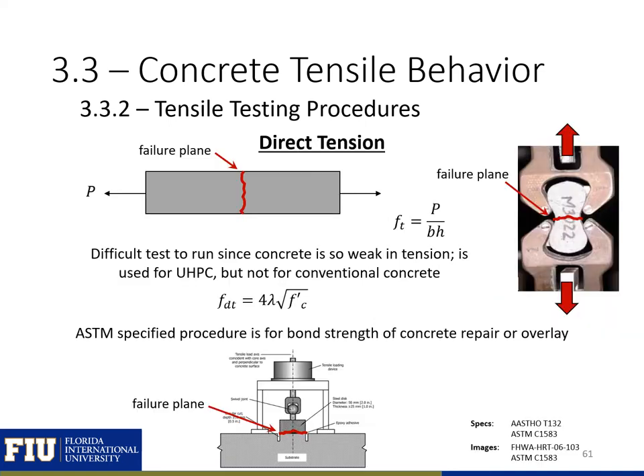The last way that tensile strength can be measured is using a direct tensile test. This test involves applying a tensile load to the concrete until the specimen fails in tension. The tensile strength can then be found by taking the failure load divided by the area of the failure plane. This is a difficult test to run for conventional concrete because it is such a low tensile strength. The low tensile strengths do not allow for any load redistribution. So if the load is applied even the slightest bit off center, the tensile failure will start on one side and will result in a lower tensile strength than the concrete actually has.